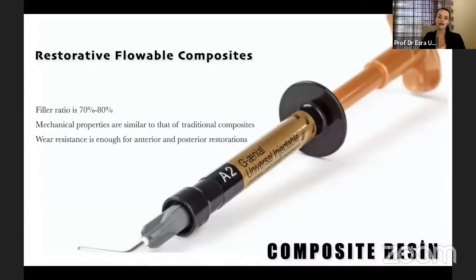And restorative flowable composites, it's a new era in composite resin. This is completely different from the classical flowable composites because their filler ratio is higher than the traditional flowable composites. So with restorative flowable composites, we can use these composites in all cavities without any traditional composite. Their filler ratio is nearly between 70% to 80%.